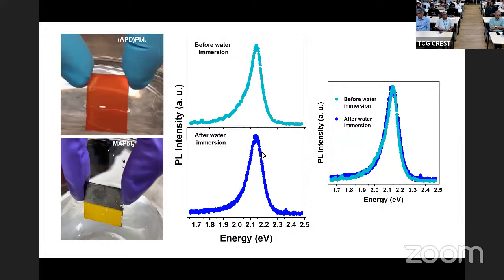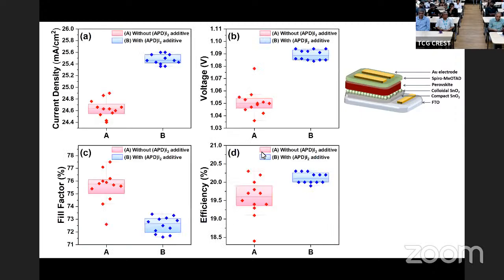But all this stability, all these good results, does it translate into good photovoltaic properties? In order to check this, we have not really explored this completely, but there are initial results that we did, forced by the reviewer, where we included this APD ligand while making the photovoltaic cell. It turns out that the red shows without the APD molecule and the blue shows with the APD molecule. There's a control with respect to that. The current density goes up, the voltage goes up. There's something else called fill factor, which actually becomes a little worse, still giving me an efficiency increase of the cell when I use the APD molecule.